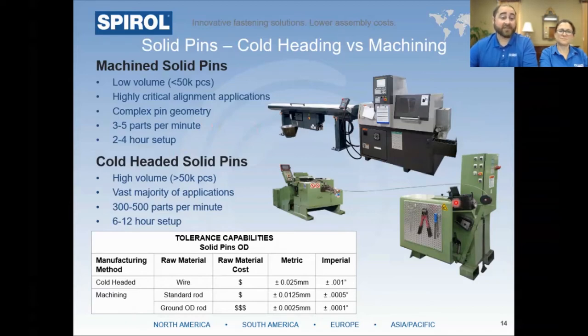With cold heading, the setup time is about 6 to 12 hours, so a much longer setup time. But you can produce parts at about 300 to 500 parts per minute, which is 100 times that of machining. So for this reason, in high volume opportunities, say 50,000 assemblies per year, cold heading is the preferred manufacturing method. Conversely, with low volume or highly critical alignment applications, machining is the manufacturing method of choice.